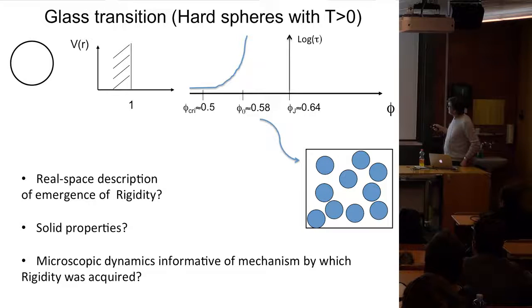What you find is that at low packing fraction there is some relaxation time tau. You can think of a particle as being surrounded by neighbors, and tau is the characteristic time by which a particle can escape from its cage. At low packing fraction this is a small time, but as you increase the packing fraction, suddenly this time shoots up. At some point it becomes so large that on experimental time scales you cannot equilibrate the system, and you have a glass. On your time scale it behaves like a solid.